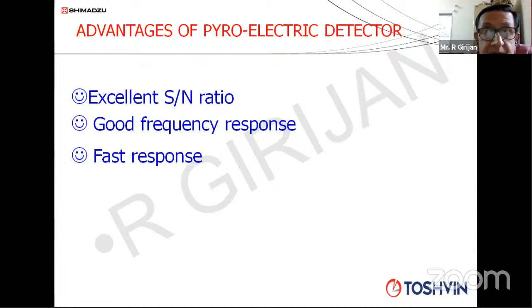By any chance, if your instrument is continuously on and the temperature of the detector material goes beyond 48 degrees, the detector response will come down, sensitivity will come down. By converting TGS into DLaTGS, triglycine sulfate is getting converted to deuterated L-alanine coated triglycine sulfate. The Curie temperature has gone to approximately 61 or 62 degrees centigrade. That means you're 100% sure, even if the instrument is on continuously for a longer period of time, this temperature will never be crossed and your detector sensitivity will never reduce. That is why we have converted this TGS material into DLaTGS material.